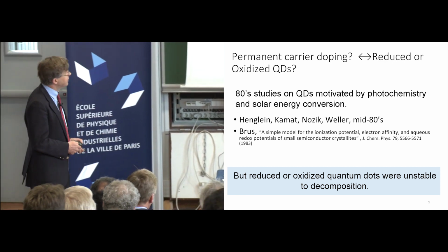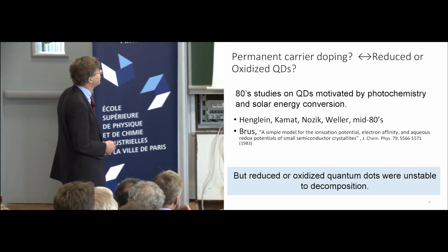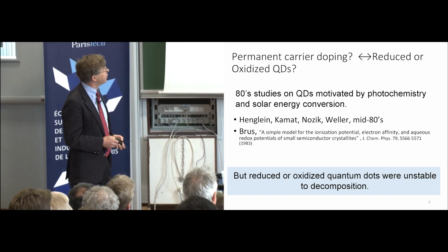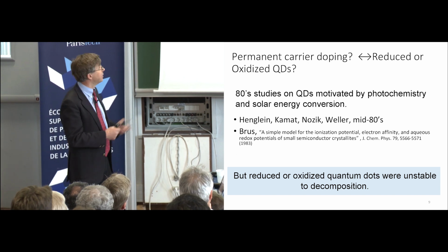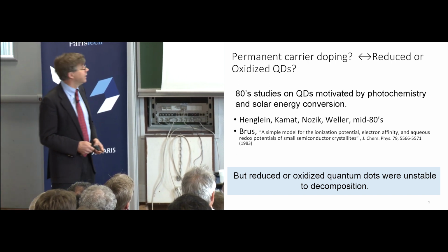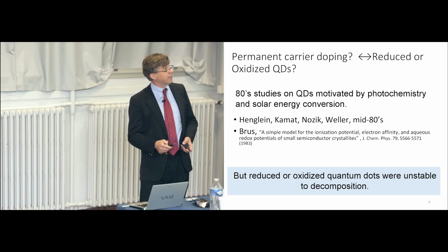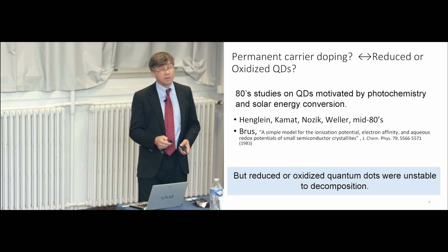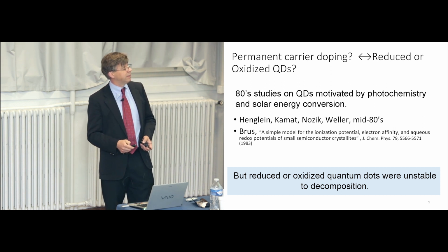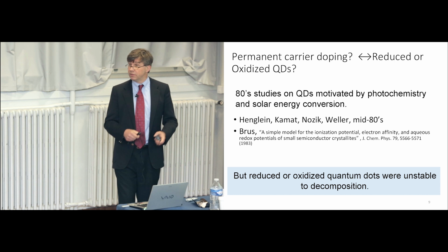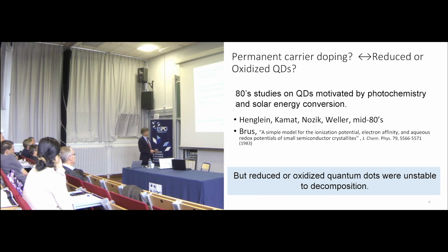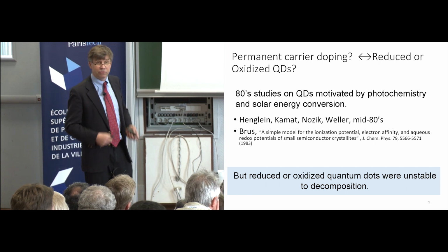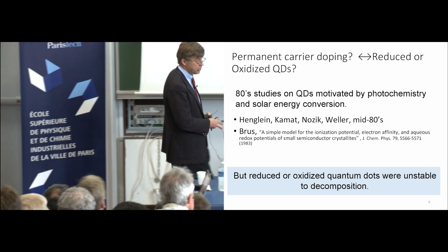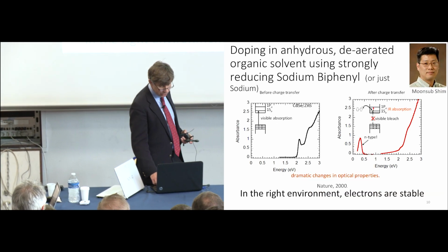And in the 80s, this was a common thought in the sense that quantum dots were motivated by photochemistry and solar energy conversion. So one wanted to photoexcite the system and separate the carriers. Most of the time, there would be a charged carrier left. This work was carried out already by Henglein, Kamat, Nozik, Weller, all of these very famous people from the early days. And Lou Brus had this very nice paper where he specifically discussed how the energy of a charged dot would vary with size. Unfortunately, all the experiments on reduced or oxidized quantum dots didn't work in the sense that they were not stable. You'd oxidize or reduce the dot, and some chemistry would go on, and the dots would degrade. So it was not obvious that it would work.